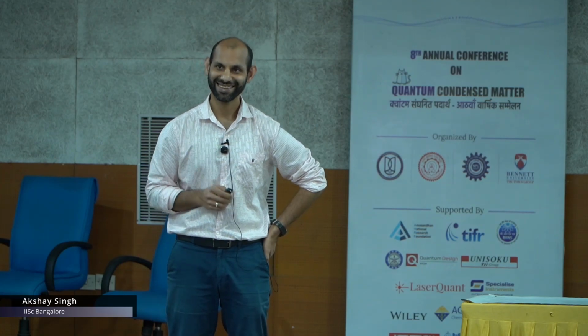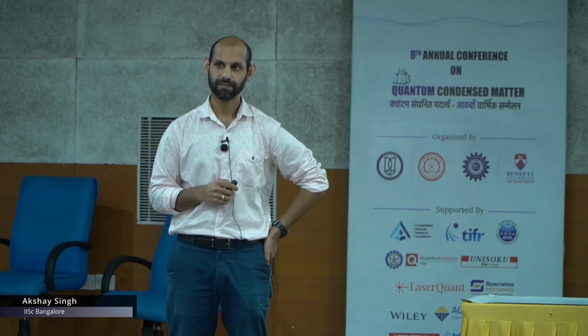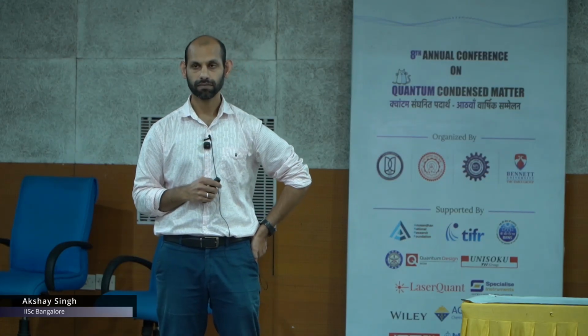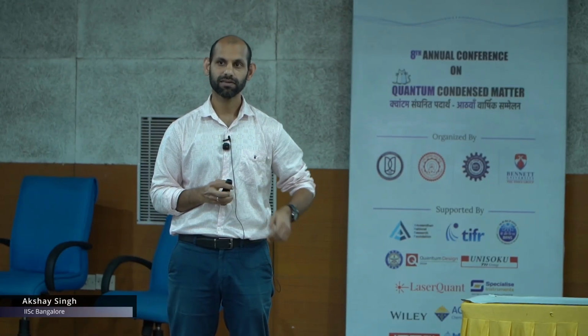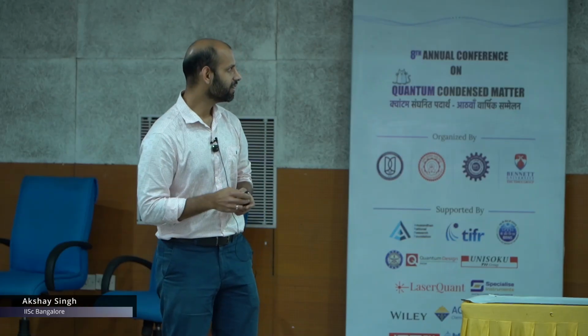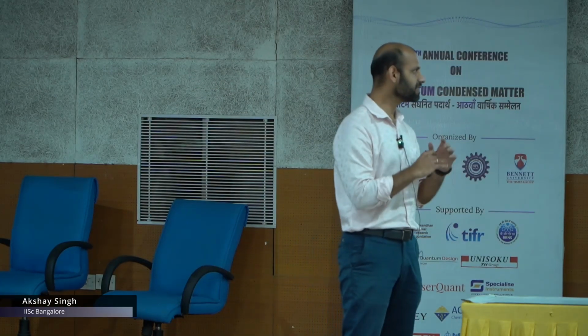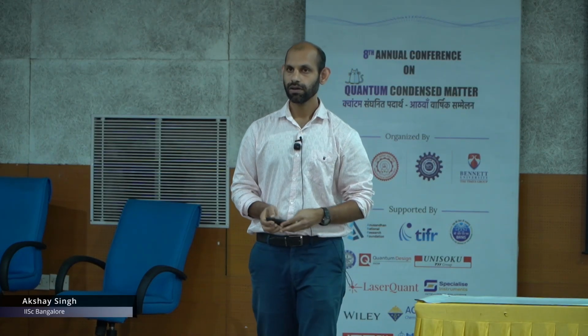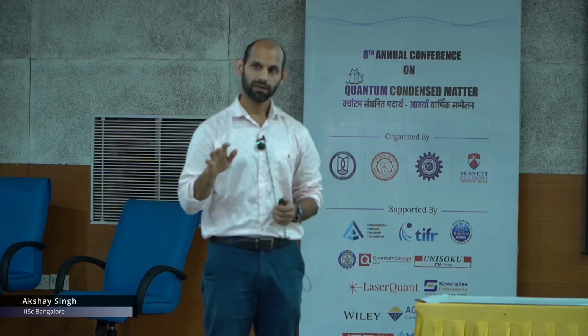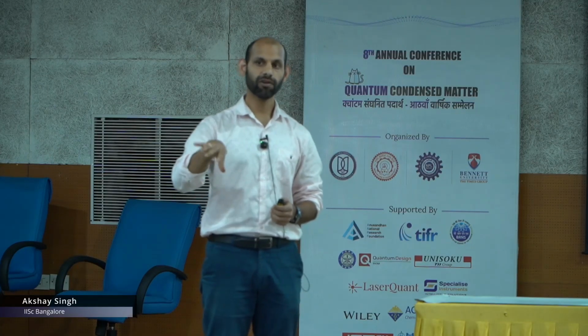Hello. Very nice talk. I just have two questions regarding the pump probe spectroscopy. Do you use any microscopy? Absolutely. How do you get rid of the pump? Great question. One sentence summary of what we do in our lab is we do transient and steady state absorption and PL with a 1 micrometer spot size. So we can do everything on the same spot, on the same sample, with 1 micrometer resolution. We have the setup for that. What is the numerical aperture? The numerical aperture is about 0.5. We use a 50x objective, but we're very careful in how we set up the optics.